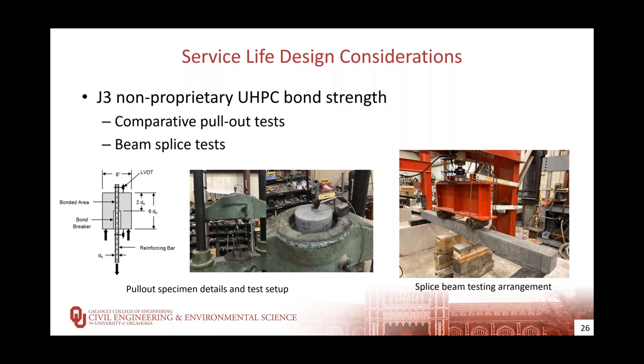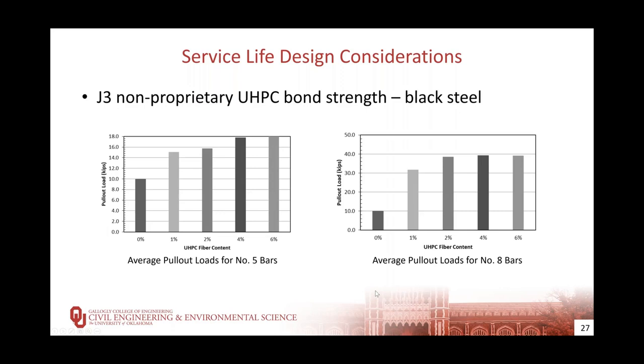The pullout test specimen was based on a method used in previous research, but had to be modified to include a very small 2d_b, or 2-bar diameter, bonded length to ensure splitting failures did not occur. The same 2-bar diameter was used for the beam splice tests. These graphs show pullout strengths for number 5 and number 8 conventional uncoated grade 60 reinforcing bars.